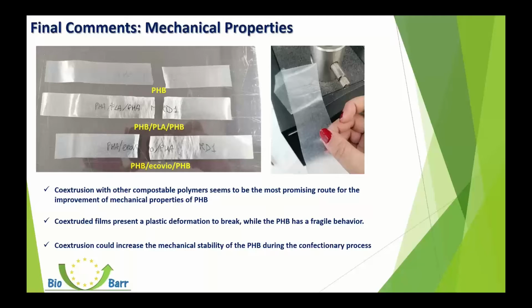In fact, as you can see also in this picture, in which are reported the samples of PHB and co-extruded PHB after the tensile testing, the co-extruded film presents a plastic deformation to break, compared to PHB that instead has a fragile behavior to break. So with the co-extrusion, we also verified that we could increase the mechanical stability of PHB during the confectionery processes, increasing the range in which this material could be sealable.